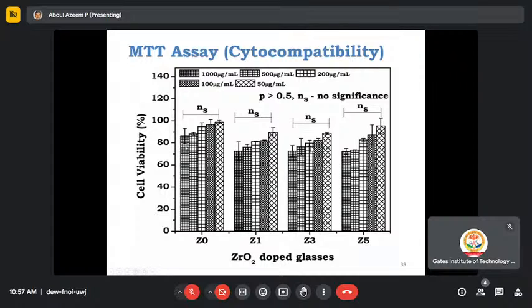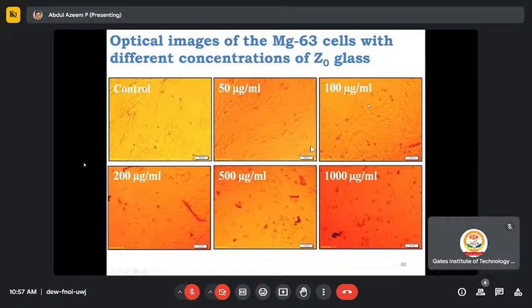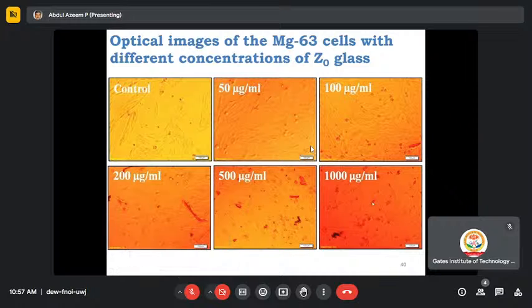According to ISO standards, if the viability of the cells is above 70%, then the material is considered non-toxic in nature. The concentration of material ranges from 50 micrograms per ml to 1000 micrograms per ml. So even at the higher concentration, we observe that our material is non-toxic in nature. And you can see the optical image of this. There are some flakes. These flakes are live cells. So even for 1000 micrograms, we can observe live cells in the optical image. So this confirms that the material I developed is non-toxic in nature.